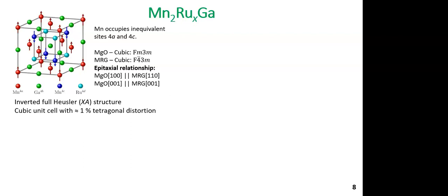It should be noted that MRG is not an antiferromagnet, because there are two inequivalent antiferromagnetically coupled manganese sublattices, with manganese occupying the 4A and 4C Wyckoff positions, as shown in the ball and stick diagram. Therefore, the two sublattices will contribute differently to the density of states, allowing for a spin gap, and the sublattice moments will have different temperature dependence, which will allow for compensation to exist.